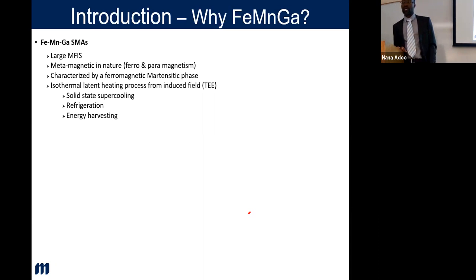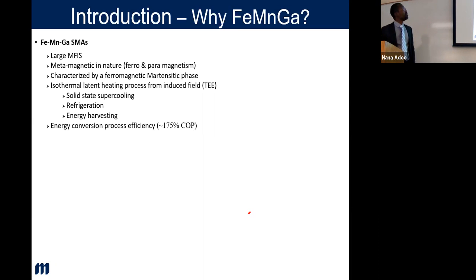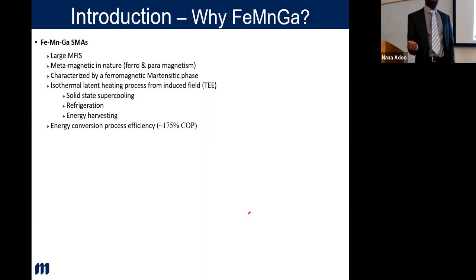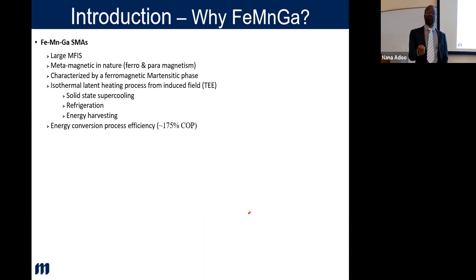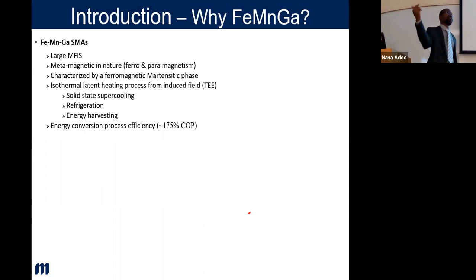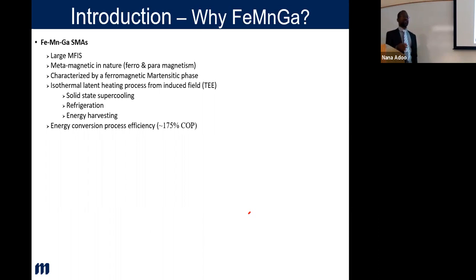Another thing is that you apply a little energy to it and you see a large effect on the opposite side, so you can use it to induce energy in systems and serve as an energy harvester. And in systems where you have energy conversion from one state to the other, when you incorporate these materials, because of that solid transformation which is going on, it increases the coefficient of performance, which is a relation of the internal energy input to the work output of the system. Research has shown that when these materials were incorporated in such systems, they bumped up the efficiency of the systems up to 175%.